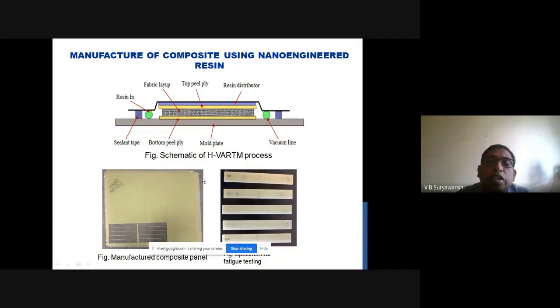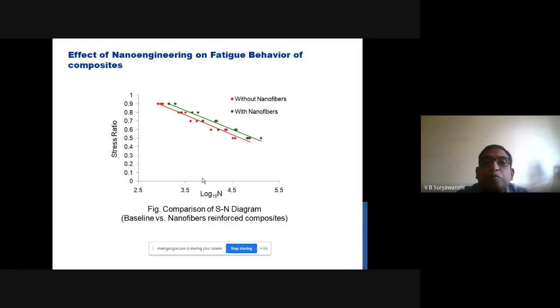What is expected? Expected is that due to the improvement in the properties of the resin, we should get better performance or better mechanical properties for the composites. And that is what has happened here. What we can see is the effect of nano engineering on the fatigue performance. So the fatigue life of, let us say, the red color is for the composite without any nanofibers. So we had not mixed the nanofibers with the resin. And we can see the curve here, which shows that the fatigue life is lesser than the green color dots. So that means with the help of the nanofibers, we could improve the performance of the composite.